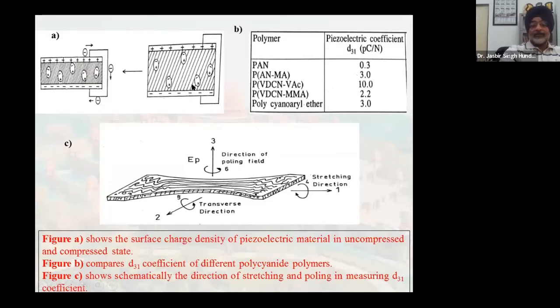But now when you compress the crystal, what happens? This dipole has also come nearer to the surface. Even this dipole has come near, and this has also come closer. In other words, there is a change in the charges here. These surface charges will change, and as a result, some current will start flowing because of the charges. If you close the circuit, the current will start flowing. And if the initial condition is this and you move the upper and lower surfaces apart, then again there is a change in polarization, and again the current will flow. So this is the basic thing which we have.